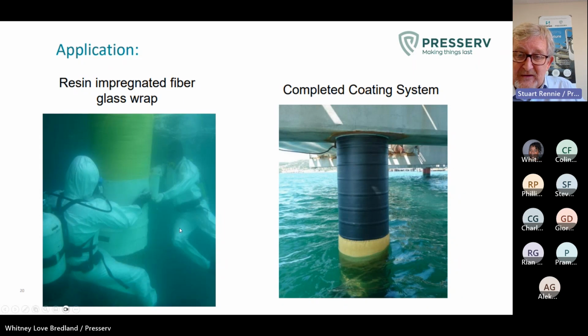Unfortunately, you've got a lot of risk there because the vessel itself will damage through impact the existing steel coating, and then to cap it off, it'll then have the friction from the rubber fender on the front of the boat rubbing up and down the factory applied coating. We've seen examples of 6 months later, we're right down to bare steel in a marine environment. So we're starting to see cumulative metal loss within 6 months on an asset that's designed to last for 25 to 40 years. So, mistake by the specifiers. This could all be sorted out at factory, but now they've got a complicated problem and are scratching their head on what do we do to stop this.